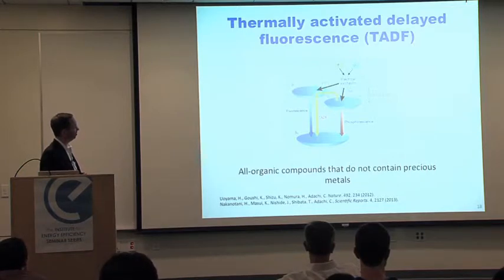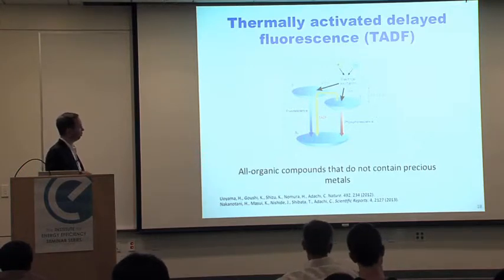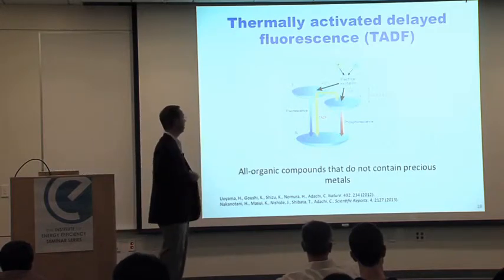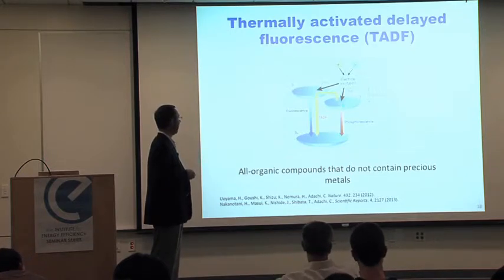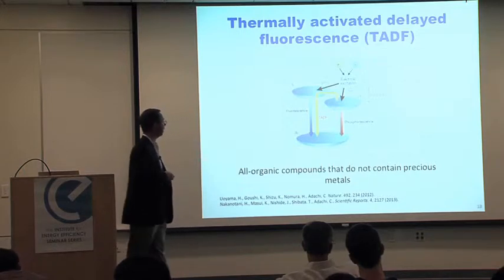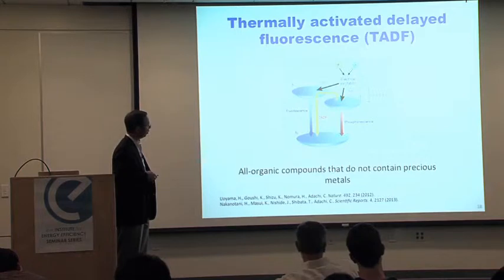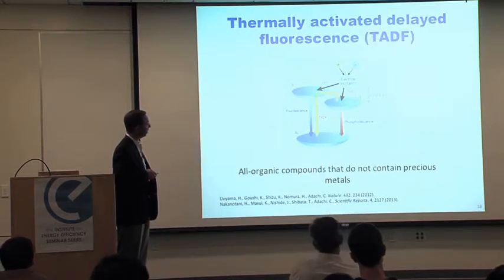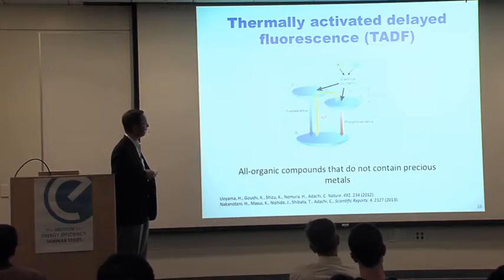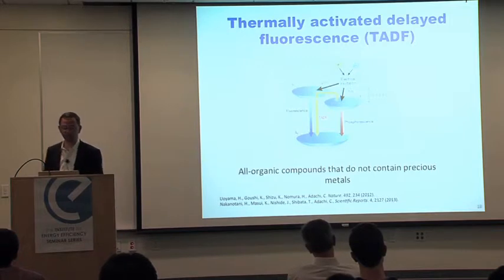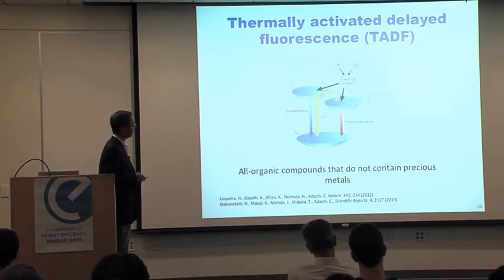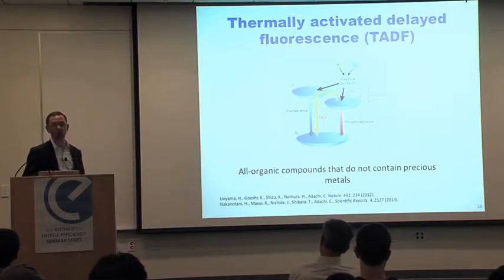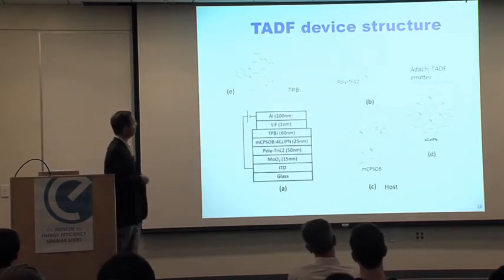And the concept here he refers to as thermally activated delayed fluorescence. And the idea is that, remember from what I said earlier, in typical fluorescent materials, you just have the fluorescence, which is the emission from the singlet excited state. Okay? And usually you don't have emission here from the triplet. But if you bring the triplet energy, or the triplet level, close to the singlet level, you can create singlet states from the triplet states through thermal activation. So you're regenerating singlet states that are emissive from these triplet states. And you can do that without having to use rare metals or rare earth elements, such as that iridium compound.